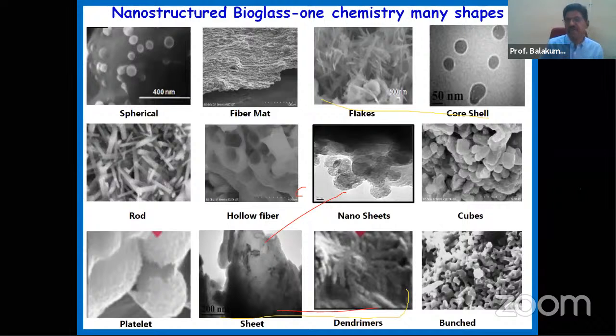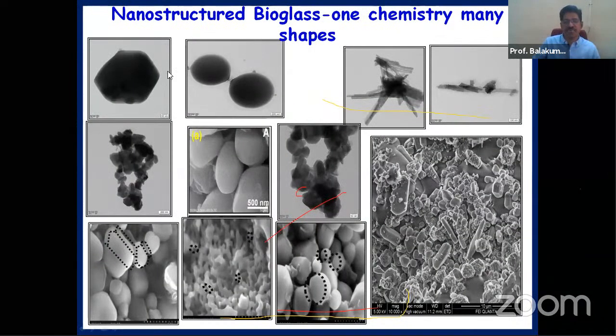In order to understand the material thoroughly, we have developed materials with a spherical structure, fiber mat, flakes, core shell, nano sheets, cubes, hollow fibers, rods, platelets, sheets, and dendrimers. In our lab, whatever chemistry we choose, we use all sorts of different wet chemical methods. We try to understand the role of the shape and the architecture. That means we take one chemistry and fabricate it in many shapes. So it is not only spherical; you can see hexagonal structures, platelets, and rods. We have developed these well.